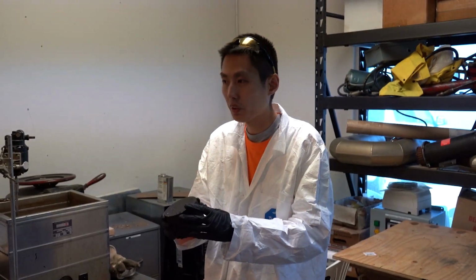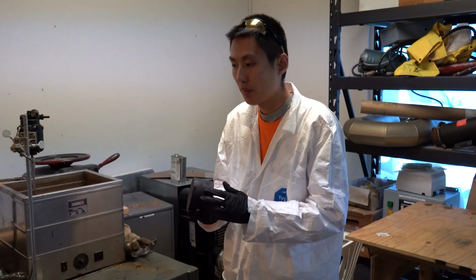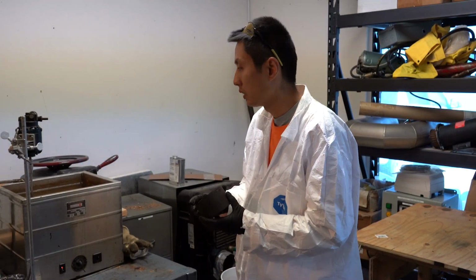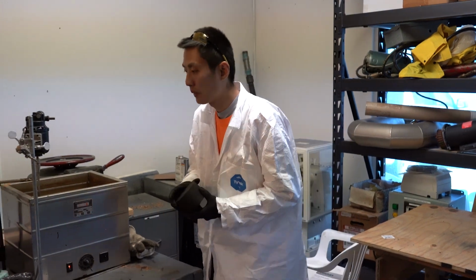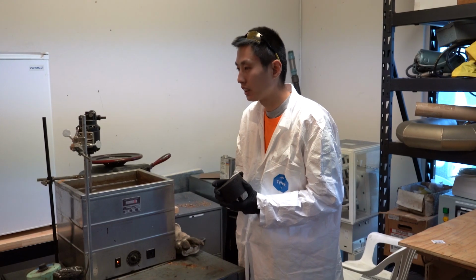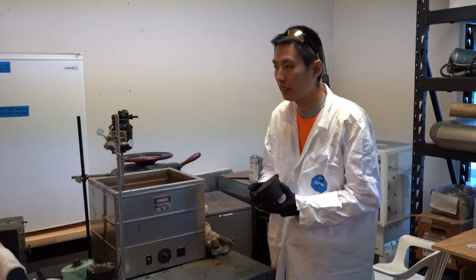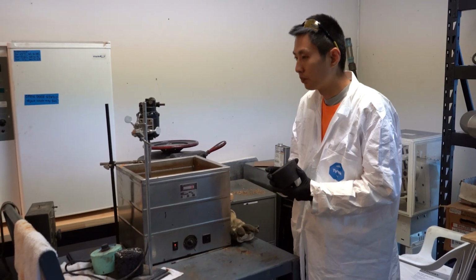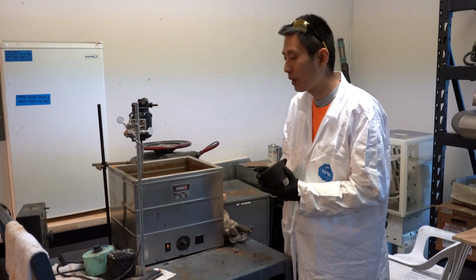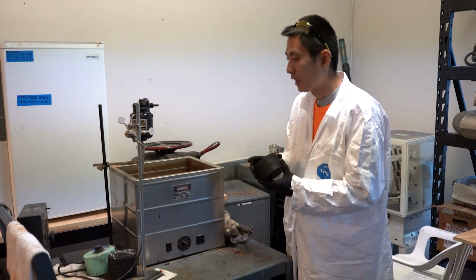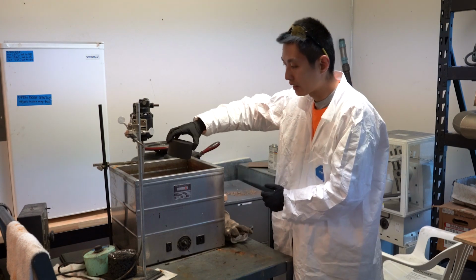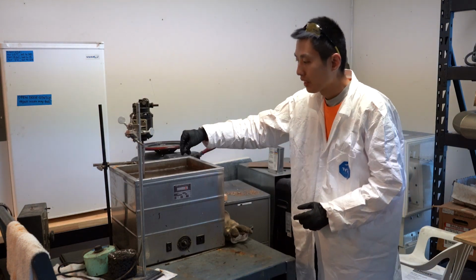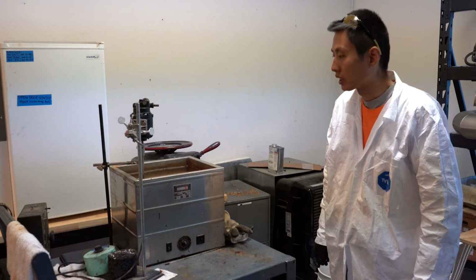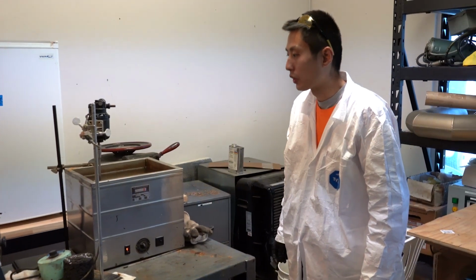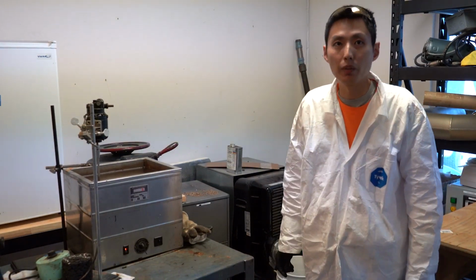After the mold, we take the sample out of the mold and measure its density, then we will do the Marshall stability test. The Marshall stability test is running at 60 degrees C to simulate the material's performance under high temperature, around 60 C in the summertime. And this is the water bath at 60 C right now. We drop it in and we wait for 30 minutes, and then we will do the Marshall compression to measure its stability and flow.